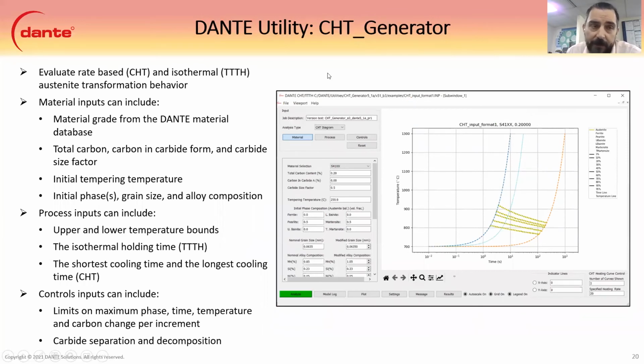Now the inverse of that is the CHT, continuous heating diagram here. And this evaluates the isothermal or TTTH or rate-based CHT austenite transformation behavior. So for processes like laser or induction heating, the austenite transformation is very rate-based. So we need to know how long to heat in order to get a full transformation to austenite. And this tool is made for that. So it works the same way as the TCT diagram.